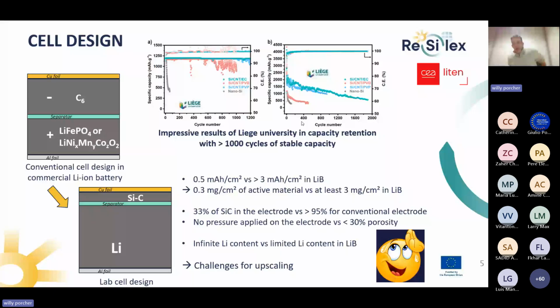I would like to address the challenge that we had at CEA compared to the result presented by Hamid before in half cells. It was this result presented, where he demonstrates stable capacity for more than 1,000 cycles. I would like to come back to the parameters that we have in half cells. In the half cells, the quantity per square centimeter is very low. It was typically 0.3 milligram per square centimeter of silicon carbon, whereas we usually are at more than 3 milligram per square centimeter in lithium-ion batteries.